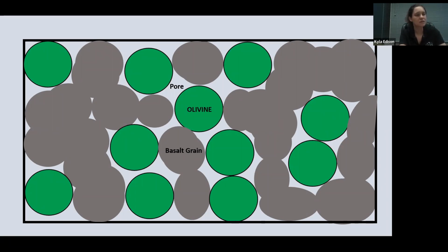And so the idea was that in a sample that's rich in olivine, when you sinter, the basalt grains during the sintering process begin to fuse. And they start to mesh together. Whereas if you have a large percent of olivine, that olivine isn't necessarily sintering or melting, it's just sitting there and warming up. And when it's not sintering, you're creating these huge gaps, which is probably causing the poor structure of the material.